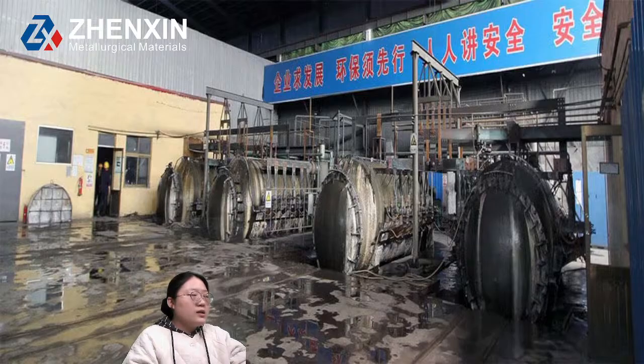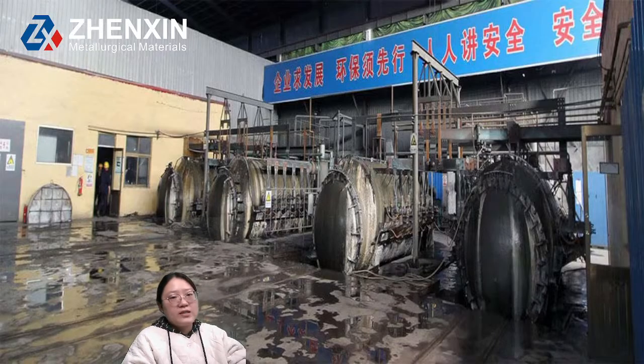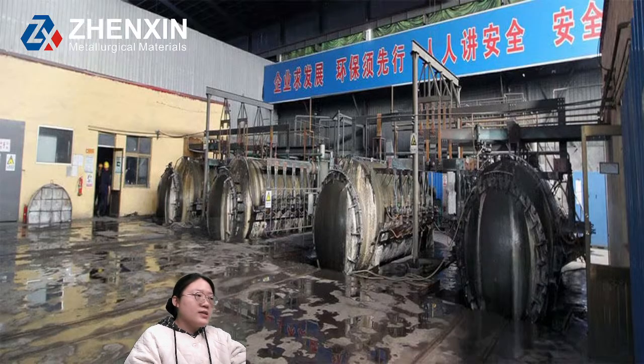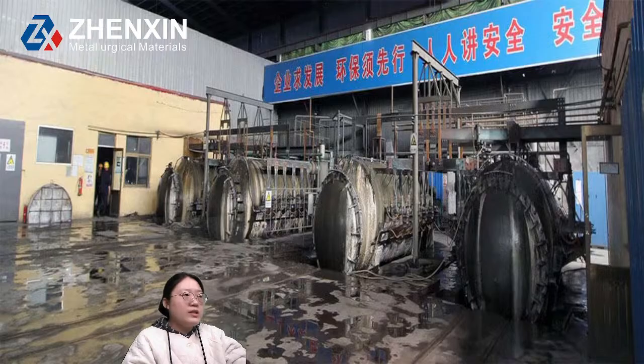And yes, let's continue. The magnesium has three key effects in molten iron. First, it reacts with sulfur and oxygen. Second, magnesium changes graphite nucleation behavior. It modifies the surface energy during solidification. And third, the magnesium suppresses flake graphite growth direction.